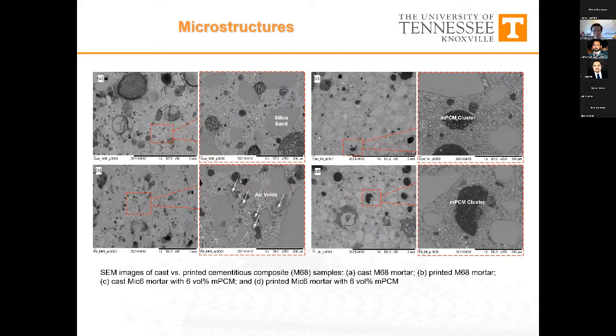So I'm just going to show very quickly the microstructures from the SEM scan that we did. This is a comparison between the cast sample on the top and the printed sample on the bottom, where on the left are the control mixes without any encapsulated PCM being added, whereas on the right we have the microparticles added to about 6% of the volume.